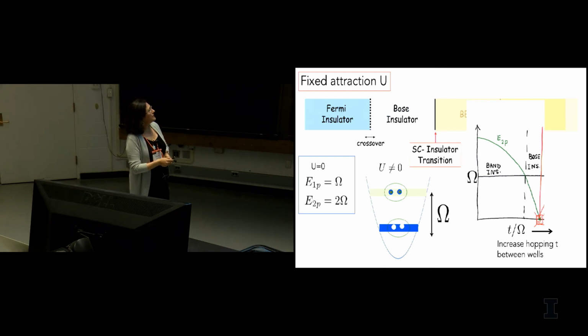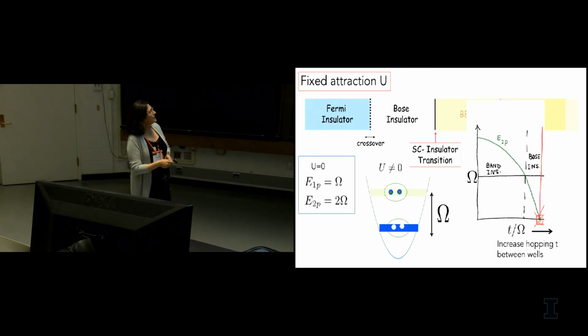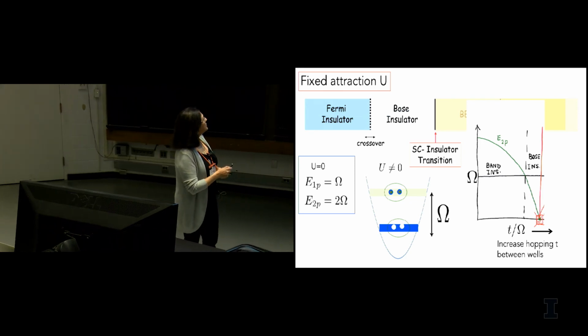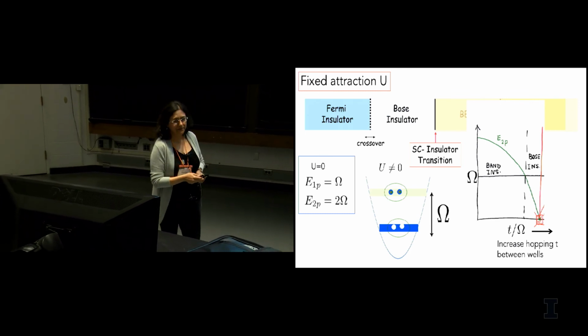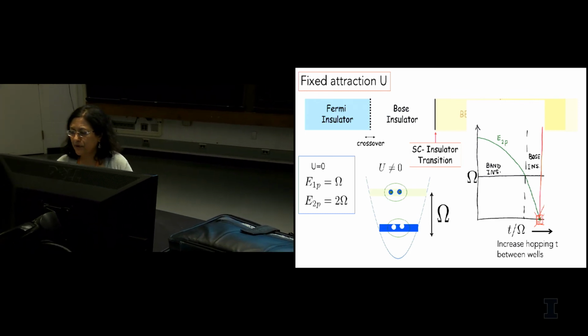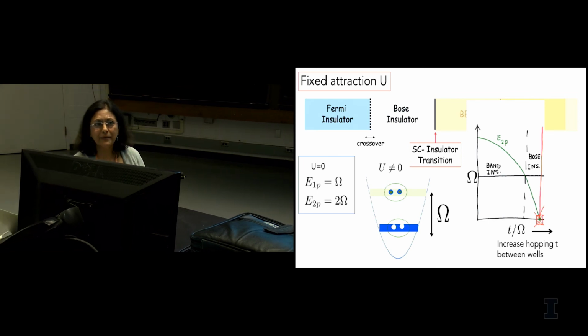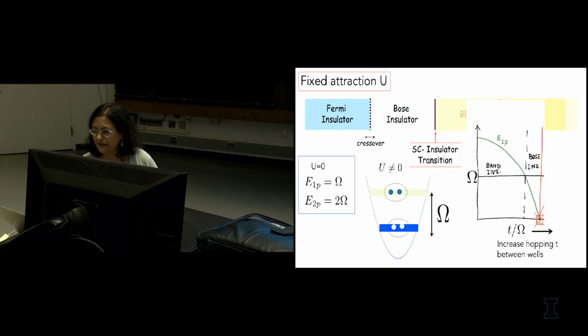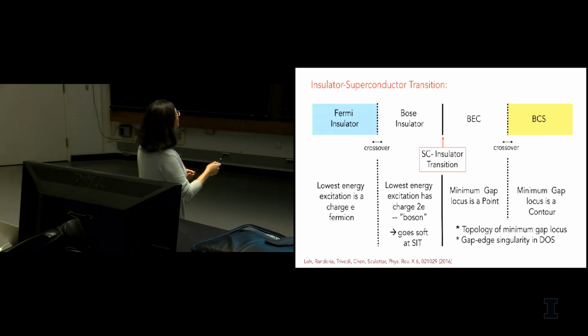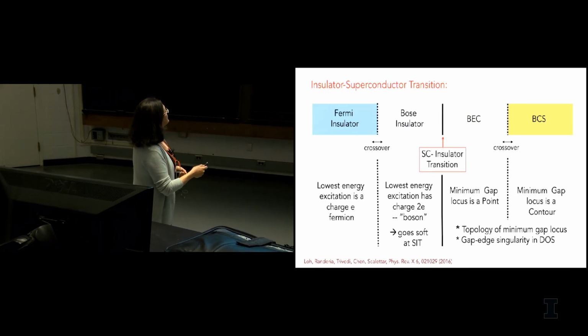So this is the E2p, which is the binding energy for 2 electrons, becomes lower at some point compared to the band insulator. And at that point, you essentially go into a Bose insulator. And so this is the progression from a Fermi band insulator all the way toward a superconductor. You go through these successive crossovers from a Fermi insulator to a Bose insulator, where the lowest energy excitation has a 2e charge, and that's what goes soft at the transition.